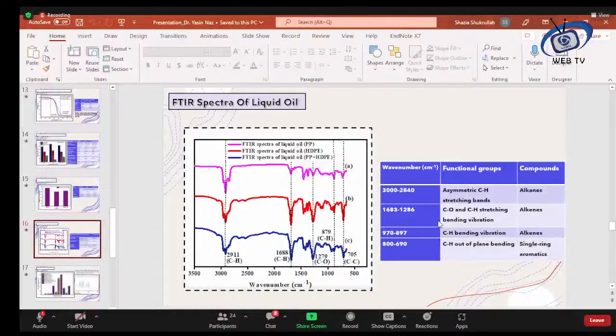So we performed FTIR analysis of this liquid product to check what kind of compounds can be in this product. So FTIR analysis shows that at higher wave numbers, we have asymmetric carbon hydrogen stretching bands, which show the presence of alkanes, and at the lower wave numbers, we got the carbon oxygen and carbon hydrogen stretching and bending vibrations, showing the presence of alkenes in the product. And at the wave numbers lower than 1000, we have CH bending vibration and CH out of plane bending vibrations, showing the presence of alkene and single ring aromatic compounds in the liquid product.